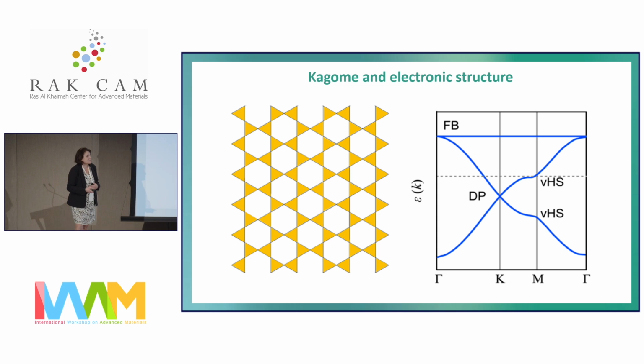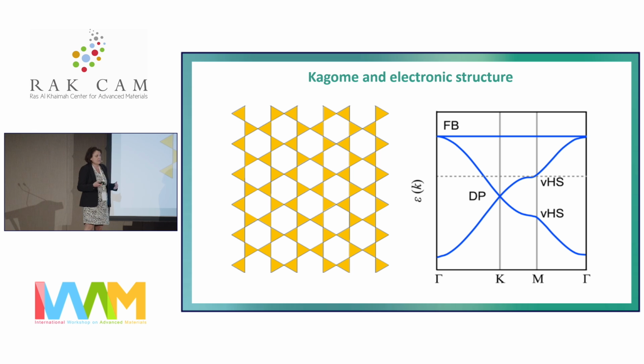People who worked on superconductivity, like me, I belong to the older generations, they know Van Hove singularities are also appearing in high Tcs at the Fermi energy, the energy which separates occupied and unoccupied states, and they are connected always with electron nesting. So we have charge density wave instabilities, spin density wave instabilities, and superconductivity, like in the high Tcs, connected very often with this Van Hove singularity. And so here you get a fingerprint simply where you have topology, superconductivity, and charge density wave instability, and this flat bands, which could lead to Kondo physics, whatever. This makes this compound so interesting.